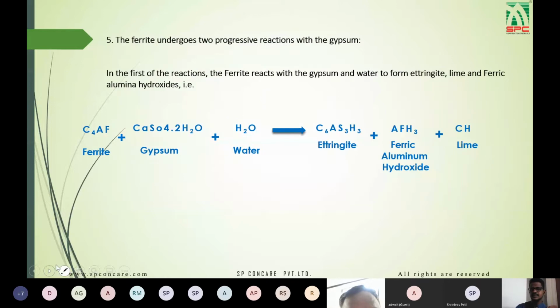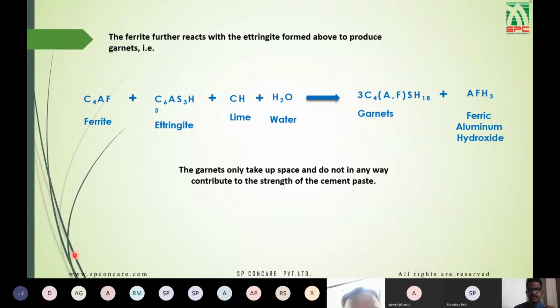So now the last reaction, the reaction of ferrite. The ferrite undergoes two progressive reactions with the gypsum. In the first reaction, the ferrite reacts with the gypsum and water to form ettringite, and produces lime and ferric aluminum hydroxide. In the next reaction, this ferrite further reacts with the ettringite, lime, and water, and produces garnets and ferric aluminum hydroxide. Now these garnets only take up space and do not in any way contribute to the strength of the concrete.